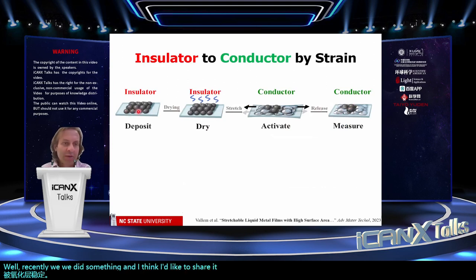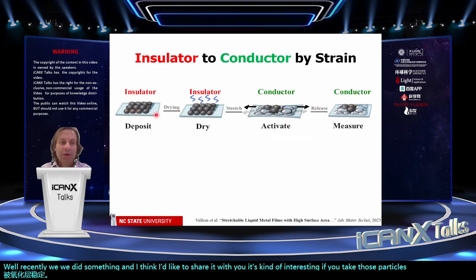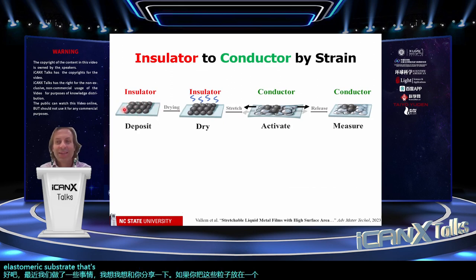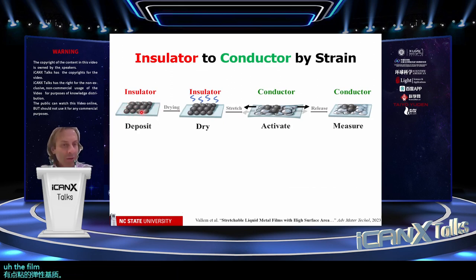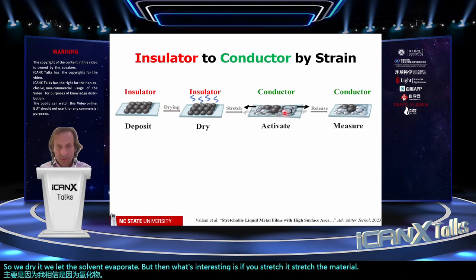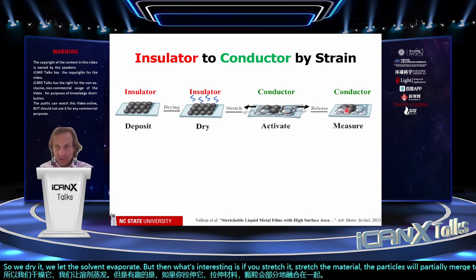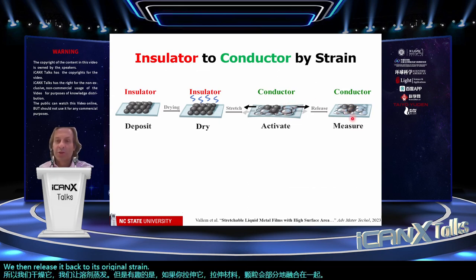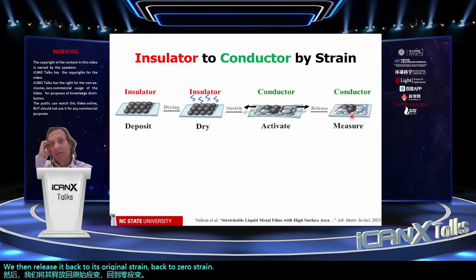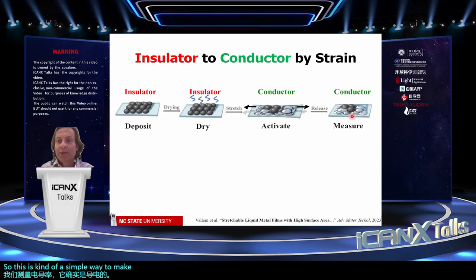Recently we did something I'd like to share with you. It's kind of interesting. If you take those particles and cast them onto a slightly sticky elastomeric substrate, the film, even though you would think it should be conductive, is not a very good conductor, mostly because of the oxide. So we dry it, we let the solvent evaporate. But then, if you stretch the material, the particles partially merge together and become a very good conductor. We then release it back to zero strain, and we measure the conductivity, and it's indeed conductive. So this is a simple way to make conductive films with high surface area.